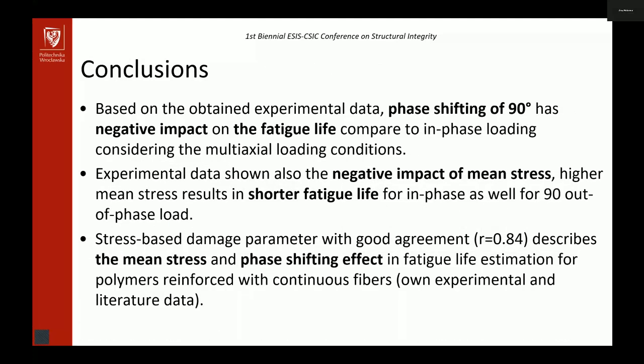So based on the obtained experimental data, the phase shifting has a negative impact, as well as the mean stress, which results in shorter fatigue life. And the stress-based damage parameter describes, with good agreement, the mean stress and phase shift effects in fatigue life estimation.